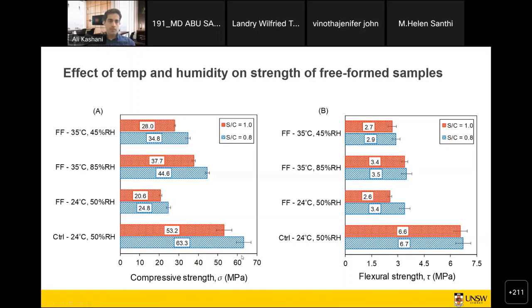So the first thing that we notice in terms of the hydration and strength development is in the samples that haven't been properly cured. The control sample has been sitting in the mold with a good sealing for 24 hours, and that first 24 hours is vital in order to get strength.